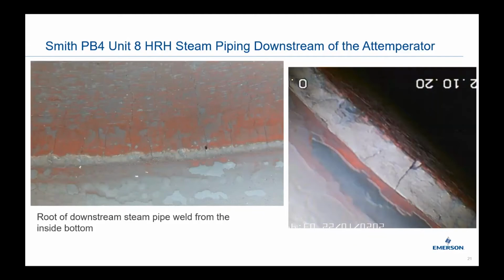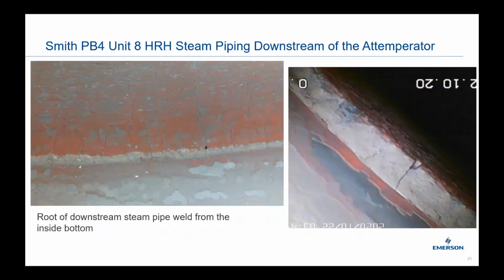And the second photo there was a bore scope that I performed on the system, and found that initial crack at the bottom weld of that steam pipe. Additionally, there is some cracking that's starting to form at the elbow immediately downstream. I don't have pictures of it, but it's just something we're monitoring. It'd be the center of the extrados, where that water is impinging on the pipe. So you're getting some unevaporated spray that's contacting the extrados of that elbow, and it is causing some cracking that we're currently monitoring.